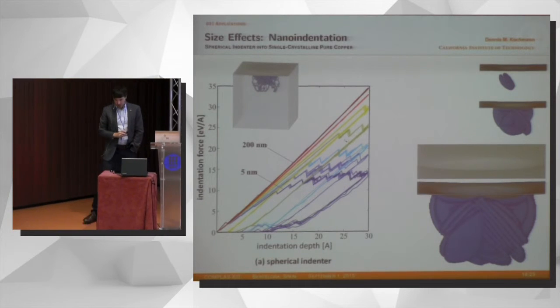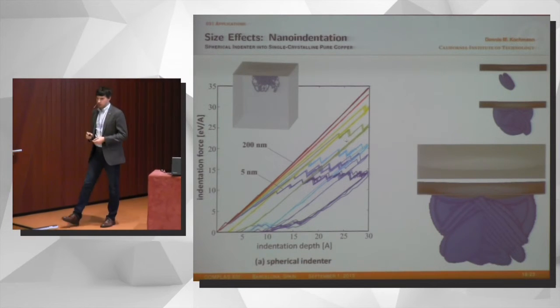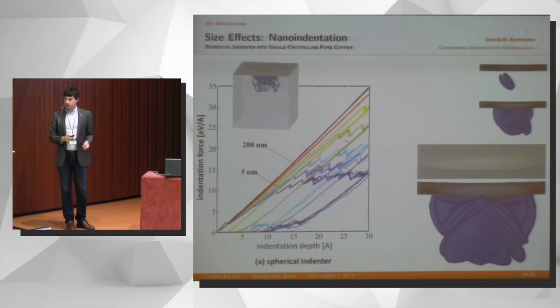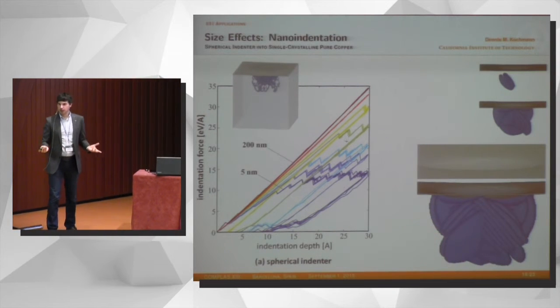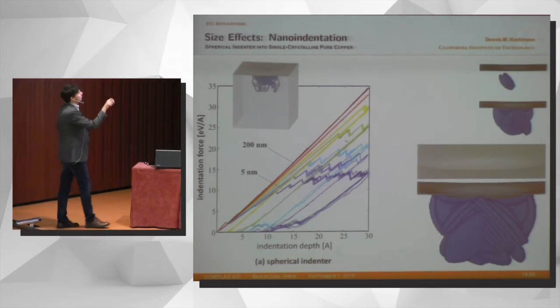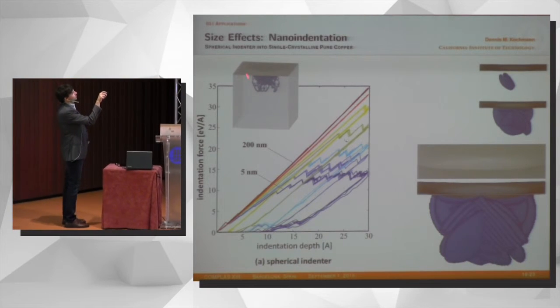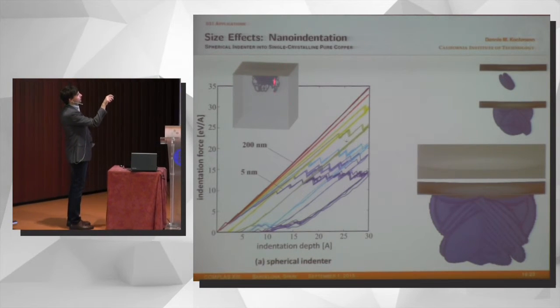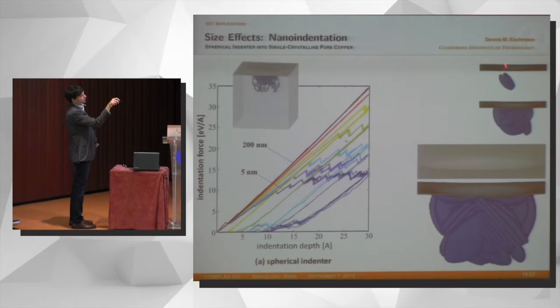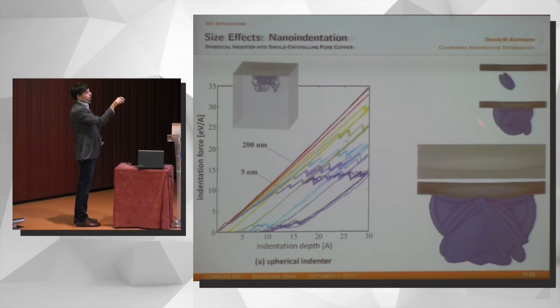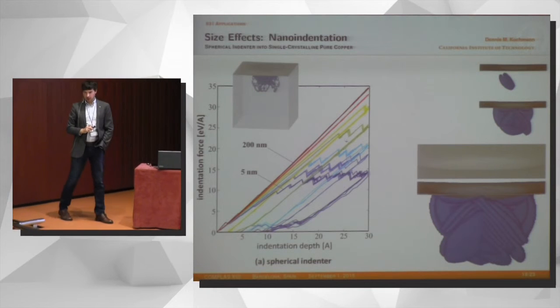So this was just one example of voids and where this is useful. This is an example of nano indentation that many people use in plasticity to identify material parameters. And this is a scenario where within atomistics we punch with a spherical indenter into the solid. We can see how a dislocation loop is created. Dislocation loops grow, they interact, and you can see interesting things happening.